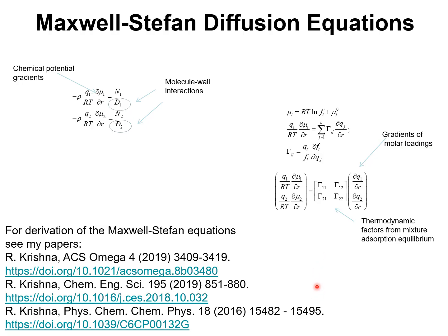The fugacities in the bulk gas phase are related to the molar loadings via the theory of mixture adsorption, such as the ideal adsorbed solution theory that relies on the use of unary isotherms.